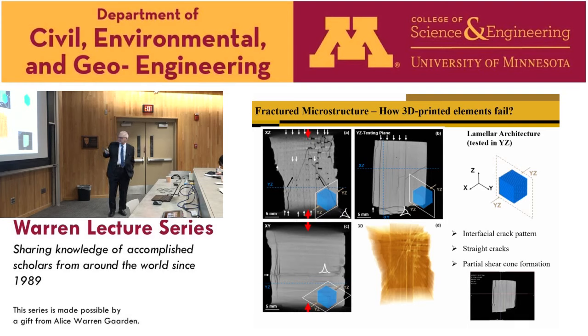And if you look at, I don't know how well you can see that, this is another one that is lamellar tested in the other direction, and you can see that there is a crack pattern that is interfacial. If you look at this movie that is playing, notice that the crack doesn't go perpendicular. It goes partially along what would be a weak interface between the filaments, and then kind of spreads in the direction that is diverted. All this meandering of the cracks consumes the energy. That increases your toughness. That increases the ductility of the problem.